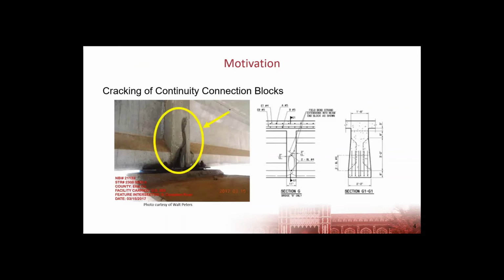This has led to a lot of issues in Oklahoma because almost every one of these bridges has cracks through those continuity connections that are caused by restrained shrinkage and creep as the bridge beams experience losses over time. So in looking at these two issues, we thought UHPC has some great potential for repair and rehabilitation of these two particular locations of girder end regions that have been damaged, as well as these cracked continuity connections.